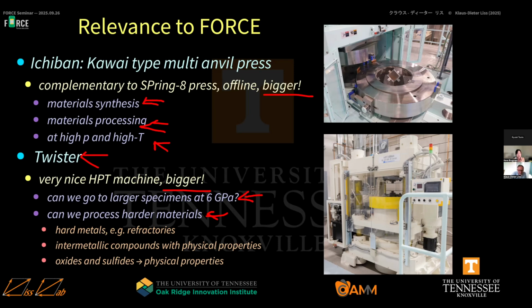Julia also asks, can the neutron diffraction or XRD measurements of the volume of the precipitates be accurate in a textured alloy? And are there ways to estimate this accuracy? You mean the volume fraction? It depends very much on the texture. For volume fraction, you typically look at the intensity of the one phase's reflections relative to the other phase's reflections. If you have highly textured material, these reflections can be non-representative because one phase may scatter somewhere else, but not into your detector. So in that case, you need to measure the full texture and get a good model of the texture.